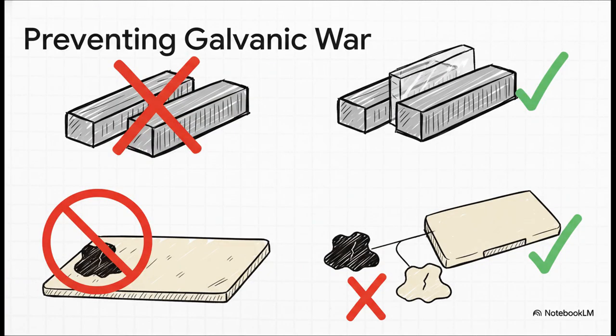Let's focus on that self-destructing battery, galvanic corrosion. How do you stop that feud? Well, the rules are pretty logical. First, try not to use different metals together. If you have to, put some insulation between them. And definitely avoid that dangerous small anode, big cathode setup we talked about. Oh, and here's a pro tip. If you're going to paint, paint the part you want to protect, the cathode. If you only paint the sacrificial part, you focus all that corrosive energy on any scratch in the paint, and you actually make things way, way worse.